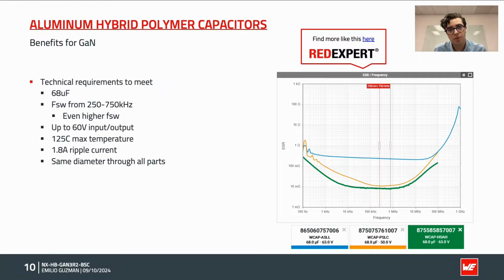And so if we switch over to the graph in the right, we can see a comparison between the three parts. The three of them are 68 microfarads and the same diameter. And so if we look at the ESR of the three, it is actually the green one, which is a hybrid, which has the lowest ESR in that switching frequency. Then above that is the polymer.